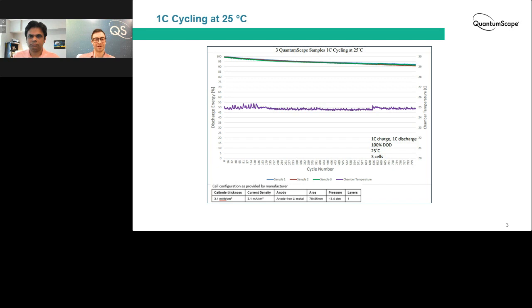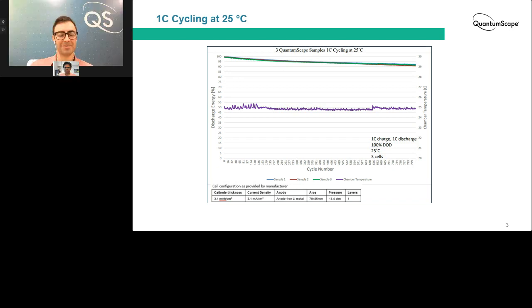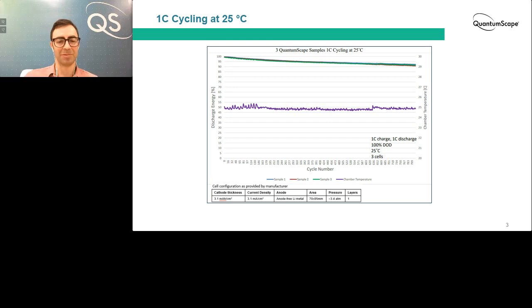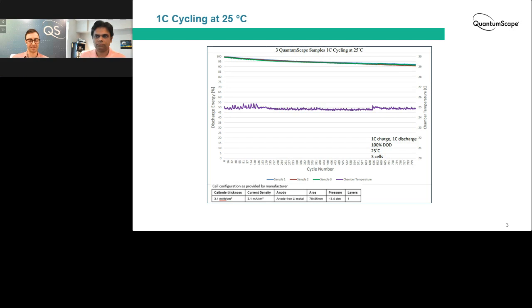And these are the cells that QuantumScape has, same genus of cells that QuantumScape has released before. It's an anode-free lithium metal anode cell of what we call a commercially relevant area, 70 millimeters by 85 millimeters, and under modest pressure of 3.4 atmospheres. These are single layer cells. So this is the main test result that the third-party lab tested and corroborated our independent tests.